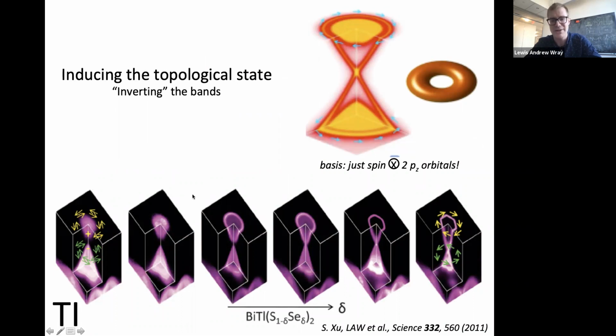So back in 2011, I was involved in work where we actually doped a material from a trivial state to a topological insulator state. On the left is the composition. We're doping in selenium to turn it into a topological insulator. Energy is on this vertical axis. You have the conduction states on top and the valence electronic states on the bottom. The energy gap here is the insulating energy gap. As we dope, the insulating energy gap closes. It opens again. We don't see the states on top anymore, but we have this crisscross. These are the surface states that I was talking about.